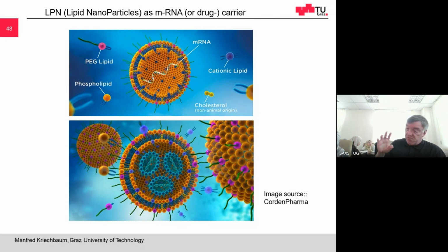And so the research was targeting to find a very suitable composition, because if you remember, the first vaccines from Pfizer had to be stored at minus 80 degrees. Because at room temperature it was degrading, and then Moderna had one which could already be used at room temperature. So it's very important to study this lipid composition, under which conditions you get a stable envelope for your messenger RNA.